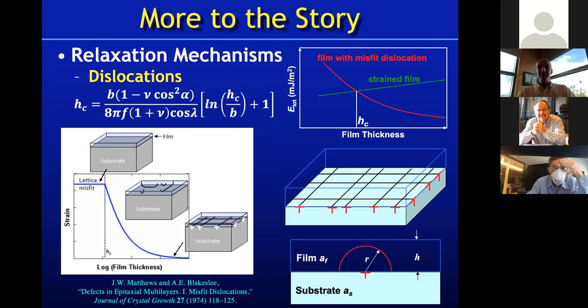There's another alternative that nature could take, and that is to relax the strain in your film. And one way to relax strain is through the introduction of dislocations. So in this cartoon down here, imagine that I have a substrate with a larger lattice constant than that of the film. So one way to relax the film is to introduce a bunch of dislocations. So here I schematically have an array of edge dislocations. And so I make that array, and this array will release that biaxial strain, but it costs energy because there's a strain field associated with each one of these dislocations. So that's going to cost me energy, and it's going to cost me energy at that interface.